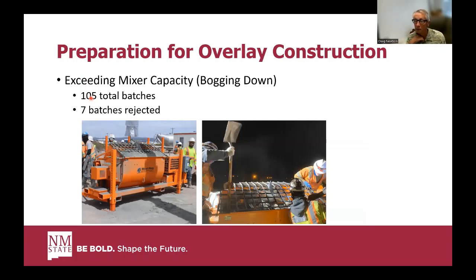1-inch overlay for basically 300 feet in each direction. We ended up rejecting 7 batches, and I guess at this point it's worth pointing out that we specified the mix design. So it was a prescriptive specification. NMDOT made that choice feeling like they had to on a pilot project with non-proprietary UHPC because the contractors wouldn't be able to come up with a mix design on their own that would